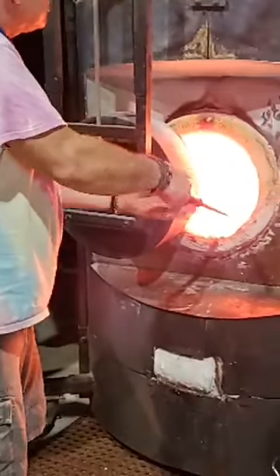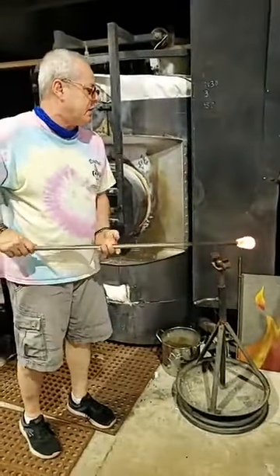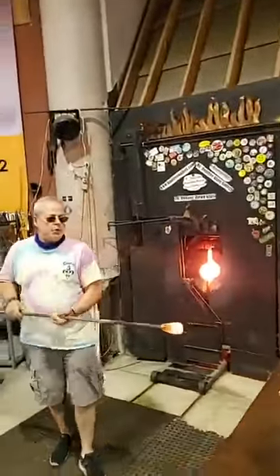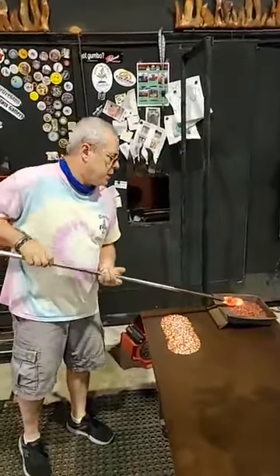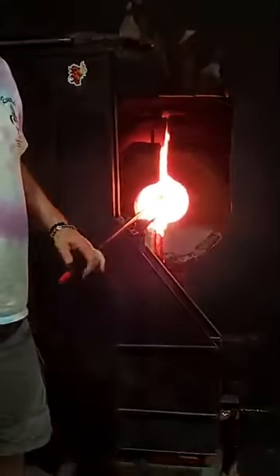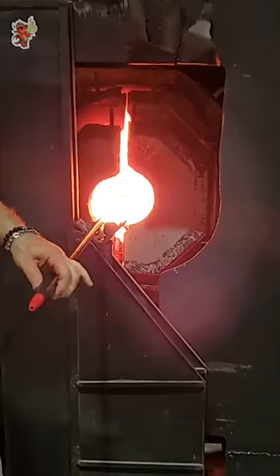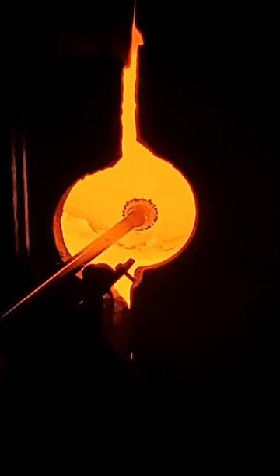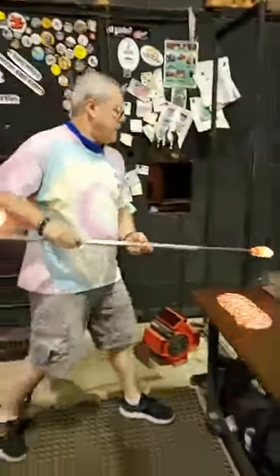I get a little glass on the end of the pipe and put little layers onto the piece. You can't just get enough for a 12-inch base on one layer. I'm going to coat this actually three times in the red — it's a nice scarlet red, so it's going to give us a nice deep color. Each time I pick up more chips and get a solid layer of color on the piece. Always turning, all the time — if you stop turning it starts to drip.